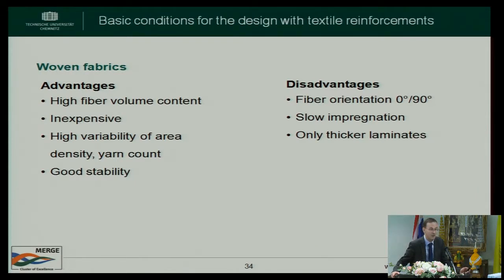Instead of this, you also can use non-crimp fabrics. So, for example, looking on woven fabrics, you can reach high fiber volume content. It's more or less inexpensive, has a good stability, but you have not so good drapability, and your fiber orientation is restricted. Weaving more or less only works in fiber direction, so 0 degree and 90 degree. You cannot weave 15 degree, 30 degree, 60 degree. Yeah? That's the problem. And as you have a high fiber volume content, it's not easy to impregnate with the matrix. So you need your matrix inside of the fibers to reach this reinforcement effect.